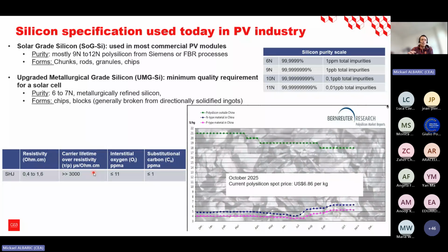And there are also specifications regarding the oxygen within these materials. It should be lower than 11 ppma, and for the carbon, it should be lower than 1 ppma. In this wafer, the oxygen is coming from the crucible used for the pulling process.